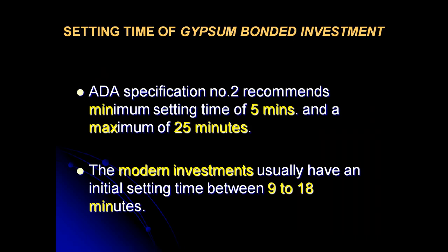Coming on to the properties, the setting time of the gypsum bonded investment: according to ADA specification number 2, the minimum setting time is 5 minutes and the maximum is 25 minutes. The modern investments usually has an initial setting time between 9 and 18 minutes.